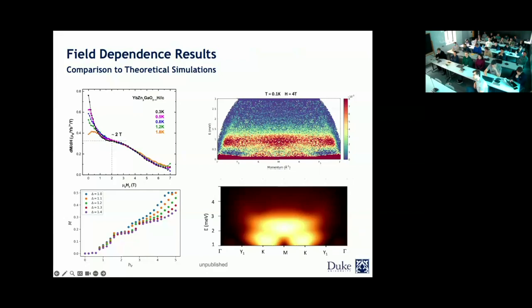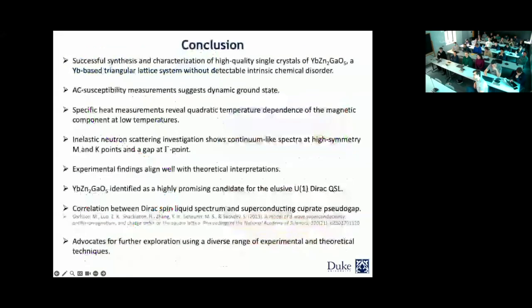And with that, I would like to conclude that we were able to successfully synthesize a new compound that, within the resolution of our instruments, doesn't have intrinsic chemical disorder. We looked at AC susceptibility measurements that show it's dynamic. We did specific heat measurements that show a quadratic term. And then we looked at the inelastic neutron experiment.